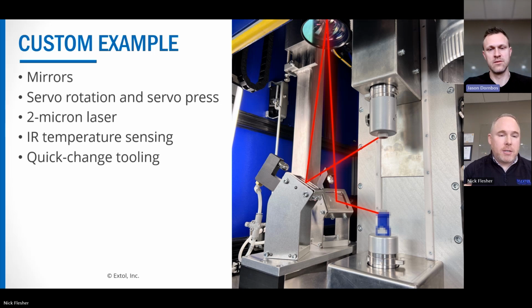In this particular case, the customer came to us with a really tough challenge, and we ended up applying mirrors. They were used to rotating the parts, so we rotated the parts while we applied the laser energy to the inside of the part. We used 2 micron. It was better at penetrating the part and going a little deeper, and they wanted that deeper heat affected zone. They wanted infrared measurements, so we used off-the-shelf temperature pyrometers or IR temperature sensors, and they wanted quick change tooling. It was a unique application where we helped this customer with a really specific request.